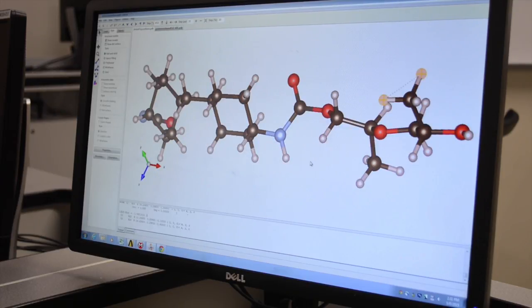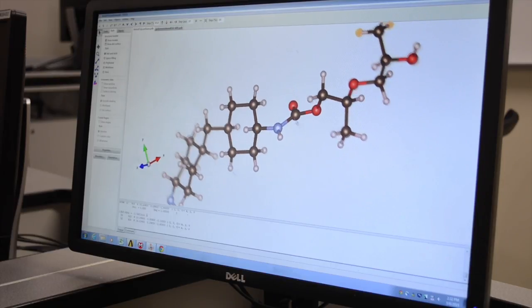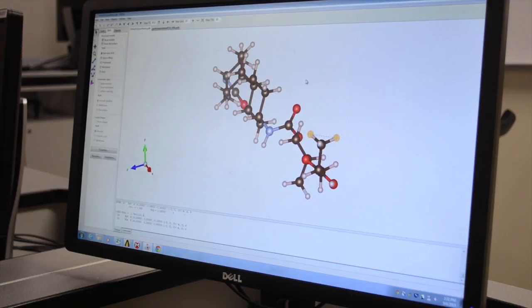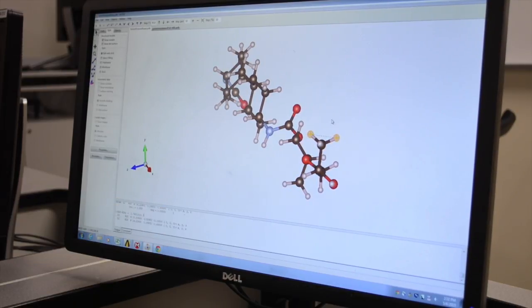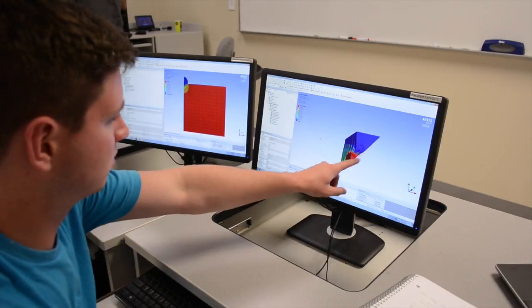Using Visualization for Electronic and Structural Analysis, or VESTA, we were able to create 3D models of our graphene and polyurethane. Working closely with John Meacham, we were able to take our 3D models and perform energy minimization, spring constant, and elastic modulus calculations via UMD's Deep Thought supercomputer. For ballistic modeling we used ANSYS Workbench for contact mechanics and impact, since we can model both nanometer and millimeter scale objects — ideal for a graphene and polyurethane composite.